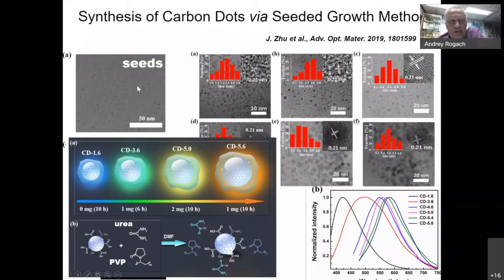Another way how we change nanoparticle size for carbon dots is the so-called seeded growth method. So we start from very small nanoparticles, we call them seed. Their size is 1.6 nanometer. They emit blue light. So this is our starting material. Then we add urea and the polymer to this starting seed, and we heat them up. This synthesis is done in DMF solvent, and depending on how much precursor we use here, we will grow them bigger and bigger. So all these numbers here tell us the average size of these particles. Our biggest particles are 5.6 nanometer in diameter.